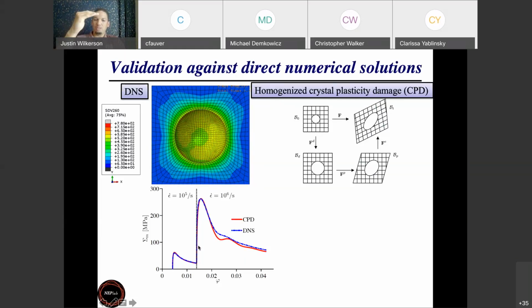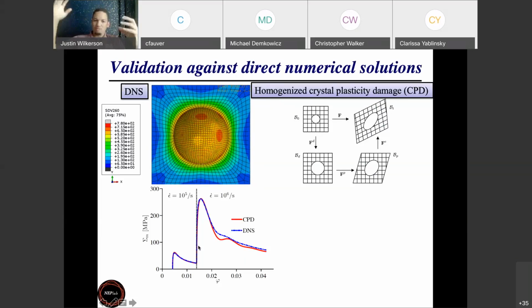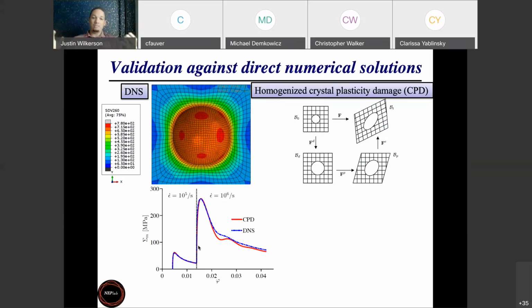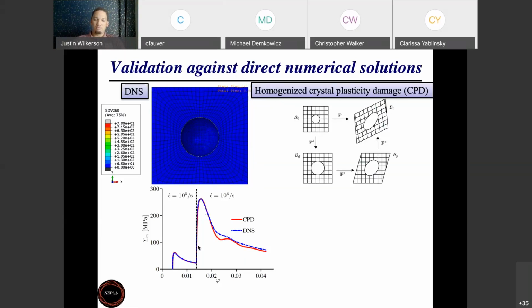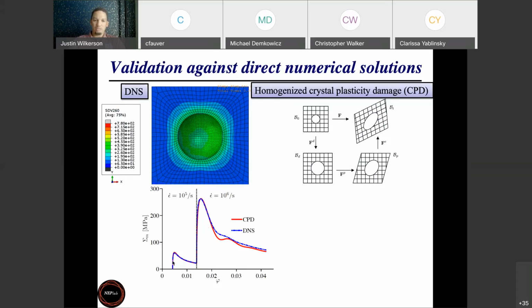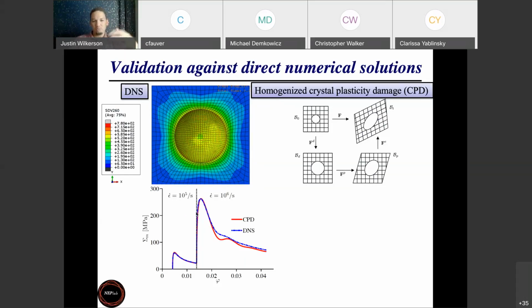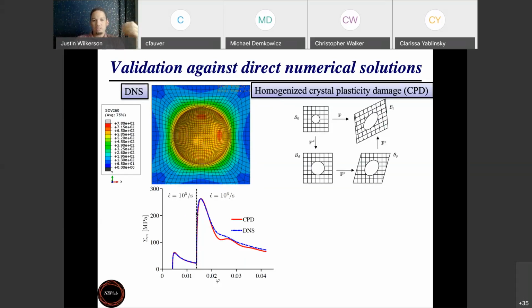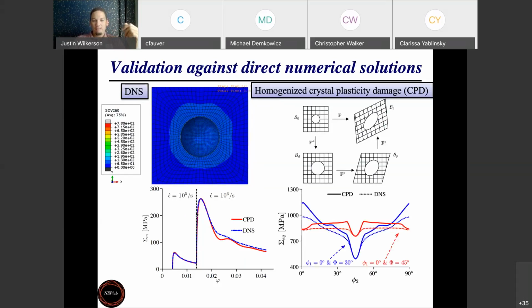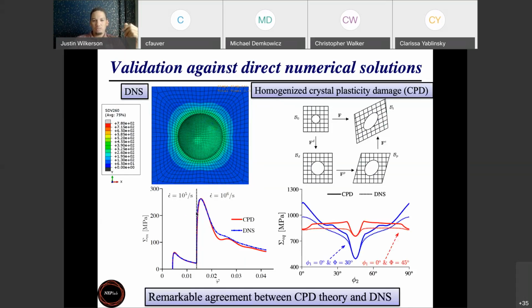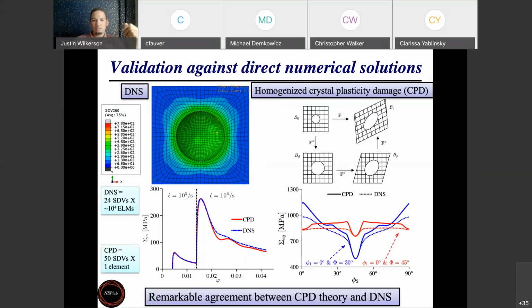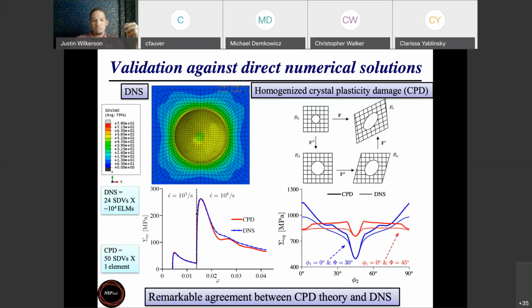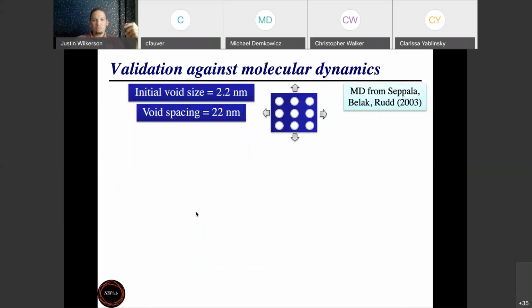So you increase the strain rate, and the void tries to grow faster, but it can't grow fast enough to relax the stress rapidly enough. So you get a very high jump in the stress. So the fact that the physics-based framework can capture such a complicated loading situation is good. And I'll skip this. And then the physics-based framework is just more efficient as well.